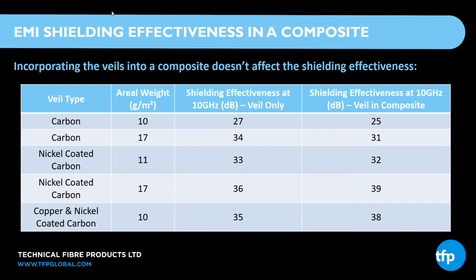But most importantly, if you look at the two columns on the right-hand side, you can see there's very, very little drop-off in terms of EMI shielding effectiveness, moving from the veil as is, so assessing the performance of the veil standalone, to the veil incorporated into the composite part. Next slide, please.